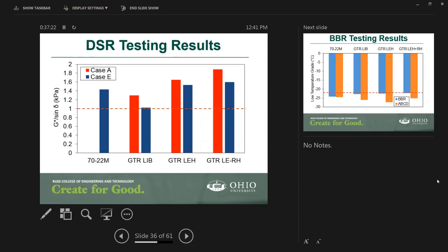What I'm showing here is two cases: case A, which is samples of GTR binder obtained after mixing, and case E, where binder samples were obtained from the production line. We did the testing on those samples just to see if there is any separation. As you can see, there is some separation, but it is insignificant. And the most important thing is that in all cases the G star over sine delta value was high. Now for the Liberty, which was the lab study, we noticed that the coarser particles of the Liberty GTR might have increased the tendency of GTR particles to separate. This is one of the things that we noticed here.